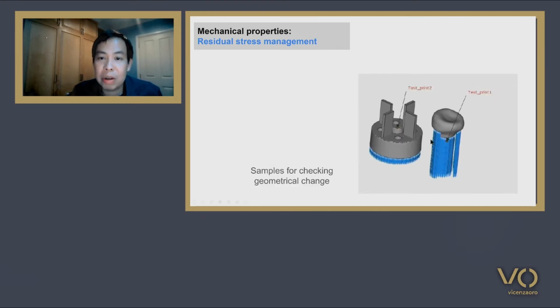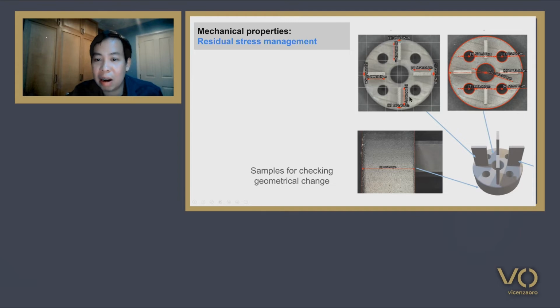So I'd like to share with you some of the test parts that we have for several print parameters. We test print the cylinder shape like this, and also some bone shapes. If we inspect closely, there are 5 different cylindrical holes here, and also just vertical slabs. And the vertical slabs are actually very difficult to accomplish, to have 99.5% density or more. So we do a lot of measurements on the inside and on the outside.